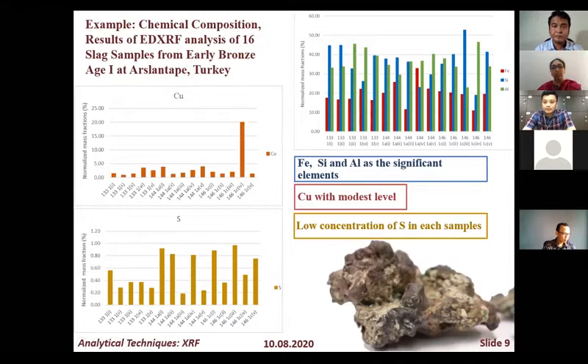So this iron, silicon, and aluminum is very significant because slag is mainly a silicate object and a mix of ferric oxide. And also we can find some copper, almost 25%, below 25%. So very few, with a modest level. This presence of copper tells us that in our sample there is a very low amount, below 1.5% sulfur. So this is how the XRF can show what type of element is present in our sample.